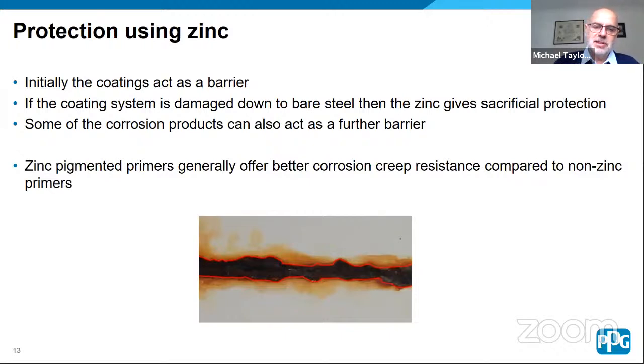In the ISO 12944 testing, actually, that's one of the key parameters. It's the spread of the corrosion. The limit to pass the test is 3 millimeters spread from the scribe in the tested panel. And the actual cyclic testing is quite a tough test. It's a 7-day test. Days 1 to 3 are a UV condensation cycle, followed by 3 days of neutral salt spray, and then 1 day of low temperature. And then that cycle is repeated depending on the test that you're doing, either to C5 or CX. There's a cycle of either 16 or 25 cycles.